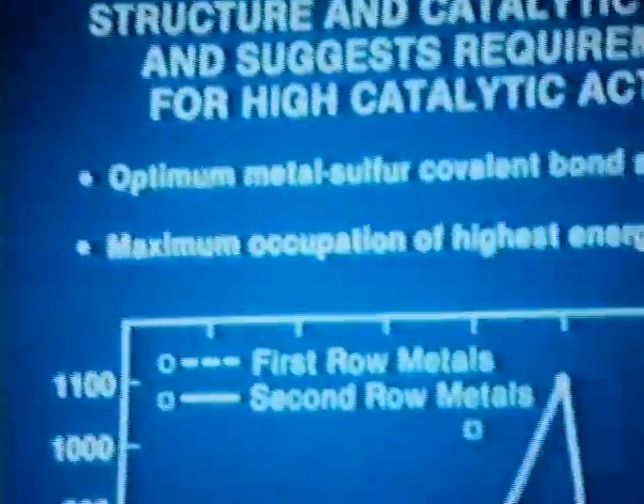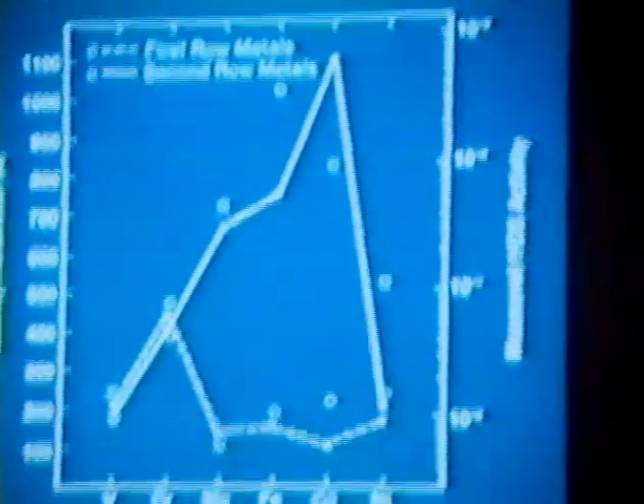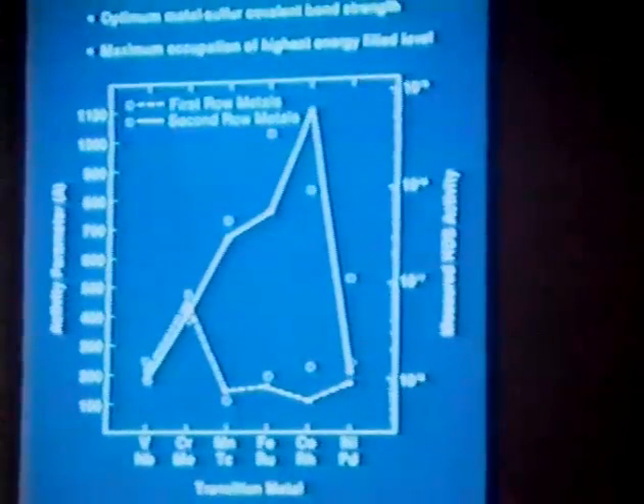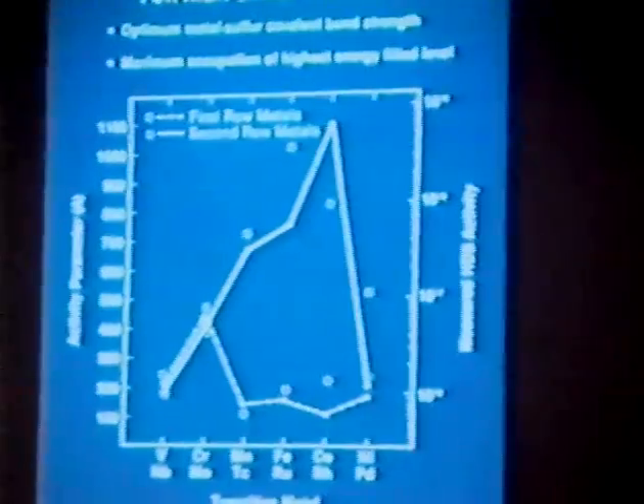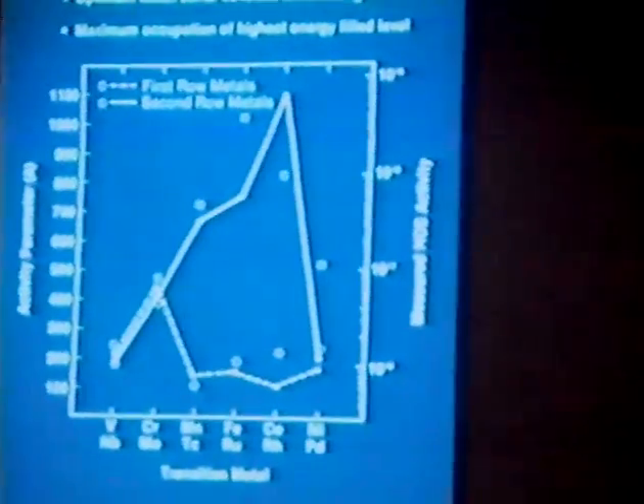Up here I'm showing ruthenium as an example, and also the maximum occupancy of the highest energy-filled levels. The metal d orbitals that are on top of this whole series, the last electrons, if you will, that go into the system — the properties and numbers of those are the things that correlate best to activity. So basically, any catalyst you're making for this reaction and the many related reactions, if you were able to do any catalyst design, you would maximize the number of 4 and 5d electrons in those orbitals.